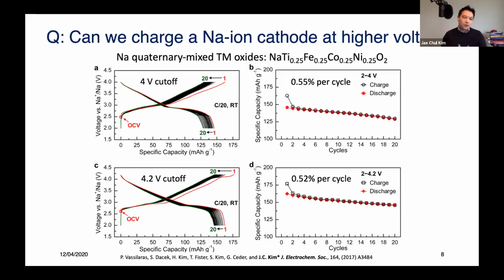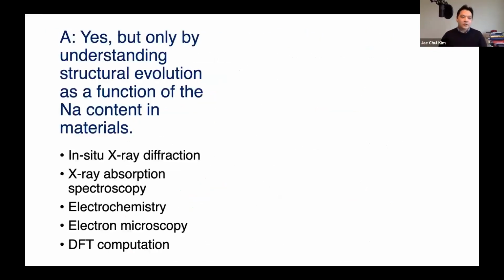So the reason why sodium-ion battery voltage was low and did not charge at high voltage is because, again, if you overcharge the material, it leaves vacancies behind, and that destabilizes the material so that your cell dies quickly. But if you know what you do and you control the structure, then you can charge your material at high voltage without losing much capacity. So simply, yes, the answer is yes, but only if you understand how the structure evolves as a function of sodium content in the material.